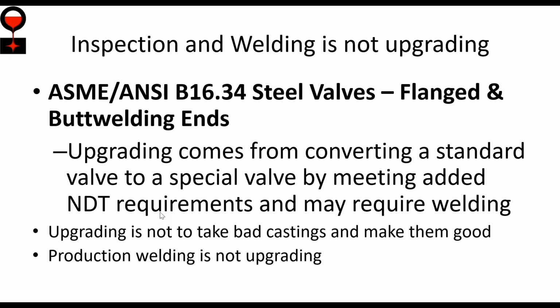So I take that commercial valve that's in a box sitting on the shelf, I take the casting out of it, I x-ray it, I find that there are NDT indications that are unacceptable under the special valve specification, and so I may have to remove non-compliant material and use welding to meet the special valve requirements. So upgrading is not an ordinary finishing operation to take a bad casting and make it good. Production welding is not upgrading.